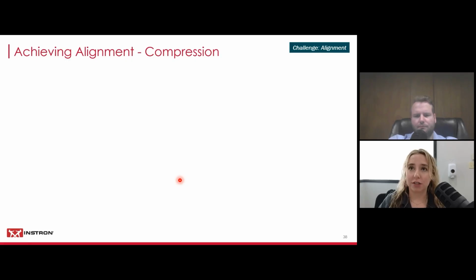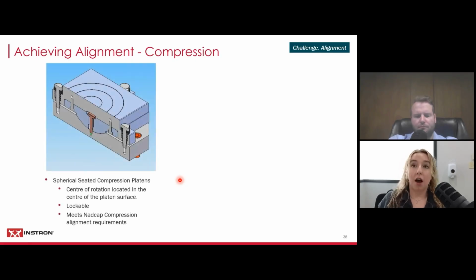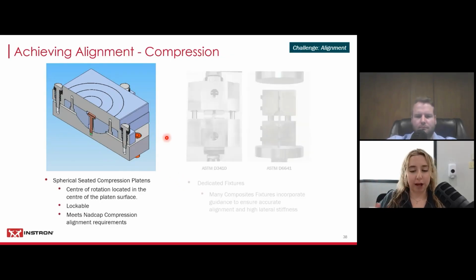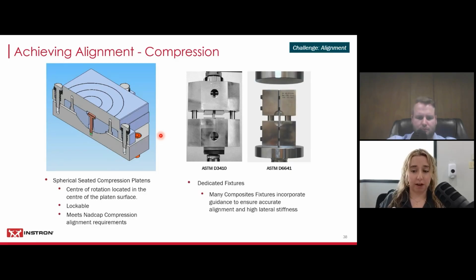So looking at compression, so we talked about tension. For compression, we typically use compression platens that have locating rings and very strong surfaces that can, again, handle the wear and tear of testing over time. And we recommend putting a spherically seated compression platen on top and a rigid compression platen on the bottom. So you drive your platens together, and once they're perfectly parallel, you would lock in the spherical seat, and this actually meets the NADCAP compression alignment requirements.